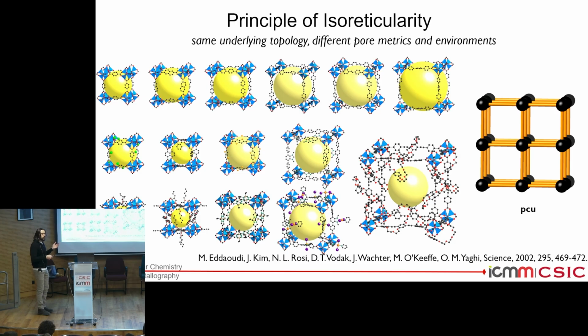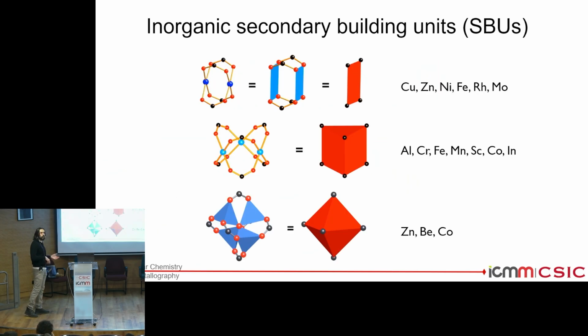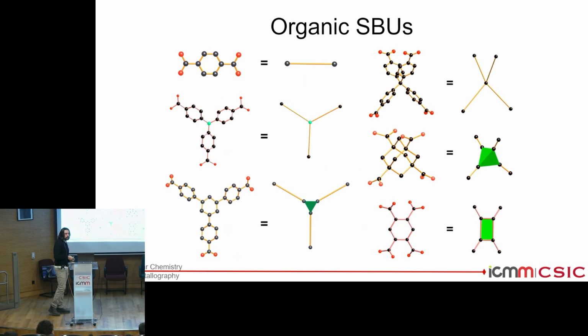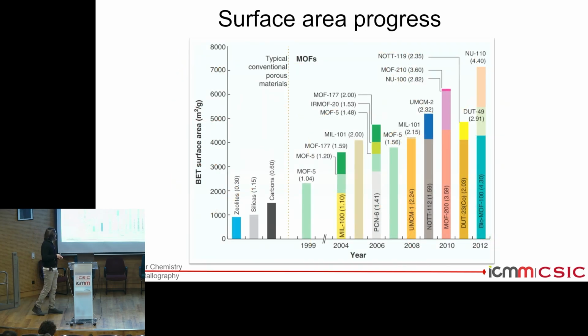And this is important because it really shows that isoreticularity can be used as a design principle. It's not just that we have a family of materials that can be expanded and modified. And this has been used over the years, not just with this, but with many other types of secondary building units. You can basically use almost any element now in the periodic table to create MOFs with different types of inorganic secondary building units. Also, for example, you can change your organic linker, have different connectivity numbers, and then you will have different types of networks. We are not having the same simple PCU network. We can have something of higher complexity because we have different types of connectivity. And it has been used. For example, I remember back in the early days there was this race to see who was able to publish the material with the highest surface area values. Back in 2012, some materials were reported to have more than 7,000 square meters per gram. Imagine this is the surface area of a football field, and you have it in 1 gram of some of these materials. So that was pretty impressive. And that was made thanks to this design principle of isoreticularity and the use of carboxylic linkers and secondary building units.